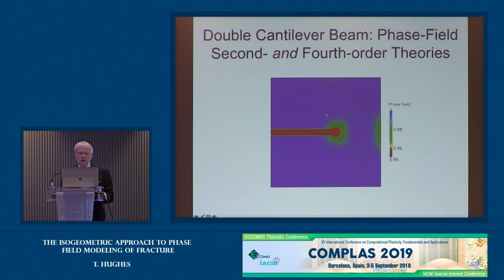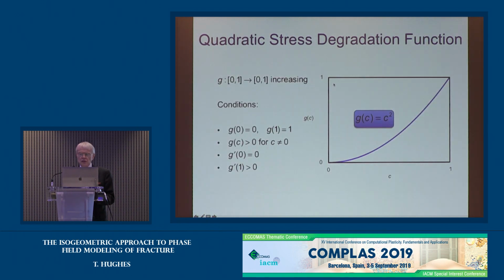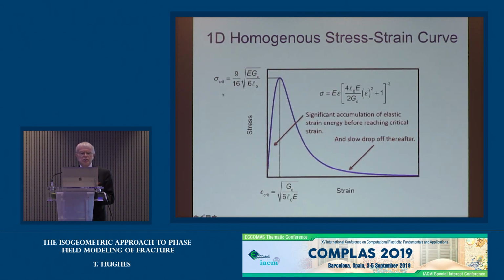Now, both theories have an issue if you use the classical quadratic stress degradation function. And I think most people are using that. I really want to point out some of those deficiencies. You can see this is a calculation where you're seeing these shadow zones here. These are diffuse damage, and they can be attributed to the second order degradation function, this function right here. What does this function change, in essence, in linear elasticity in one dimension to this stress-strain diagram? So you have an actual significant accumulation of elastic strain energy before you reach the critical strain, and then you have a very slow drop-off thereafter. Okay. So you can calculate that very simply.